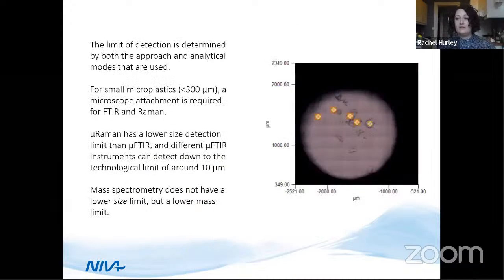The limit of detection for these techniques is determined by both the analytical modes that are used and the overall approach. The sample processing that you perform prior to chemical characterization may also affect this limit. As mentioned, a microscope attachment is necessary for detecting smaller particles when using vibrational spectroscopy, for example. If you have this attachment, you can get down to around 10 microns for FTIR, and actually even smaller, in the submicron range, for Raman spectroscopy, depending on the exact instrument that you have.